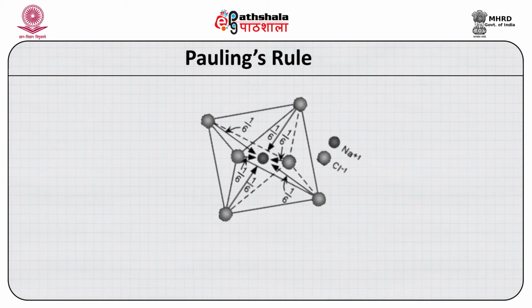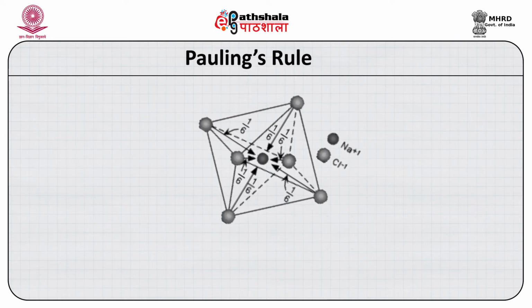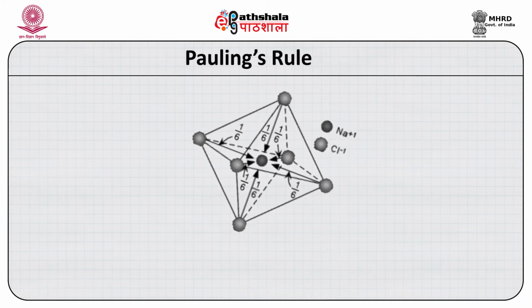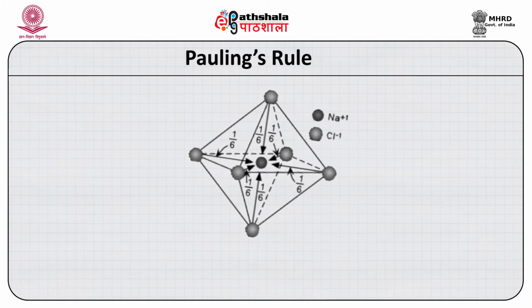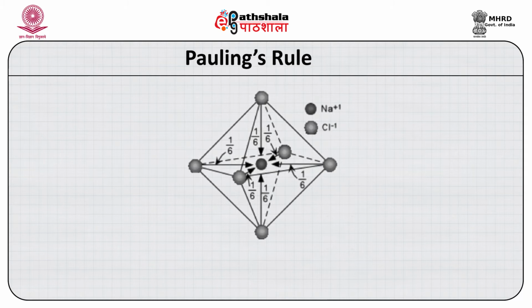In the case of NaCl, where the charge is exactly balanced on both the anions and cations, the bonds are of equal strength and they are called isodesmic bonds. In other cases where the bonds are different, that is, the charge is not equally balanced by cations and anions, they are called anisodesmic bonds.